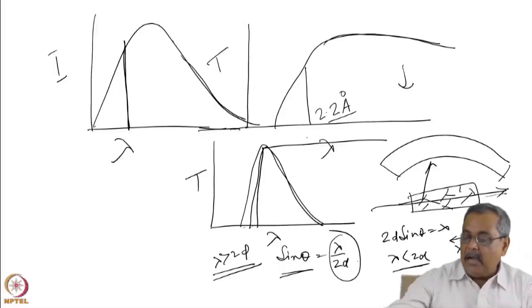Now, I told you I had a beryllium oxide filter, cooled. The beryllium oxide filter was cooled because if I don't cool the polycrystalline block, which is acting as a filter, it will cause thermal scattering of the neutrons, which is undesirable. I want a sharp cutoff. I want neutrons of wavelength below the lambda cutoff to be completely stopped from going. So that's why we used to cool the beryllium oxide polycrystalline block. Now we have a velocity selector.